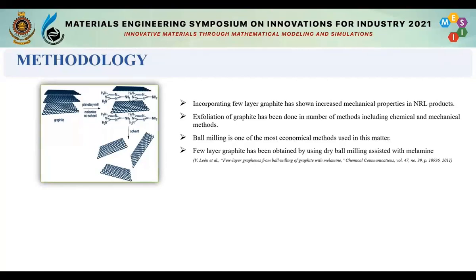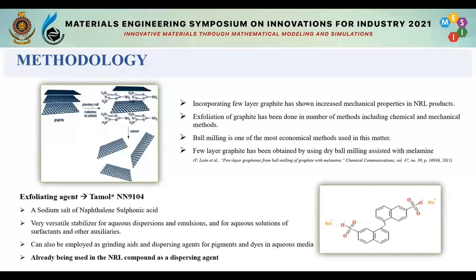And also we came across an attempt where melamine has been used as a grinding agent in dry ball milling assisted exfoliation technique. After further considerations, we decided to use Tamol NN9104 as the exfoliating agent in our process. So Tamol is a sodium salt of naphthalene sulfonic acid, which is already being used as a dispersing agent in natural rubber latex film manufacturing. This fact already guaranteed us that our final exfoliated graphite will be easily compatible with the natural rubber latex.